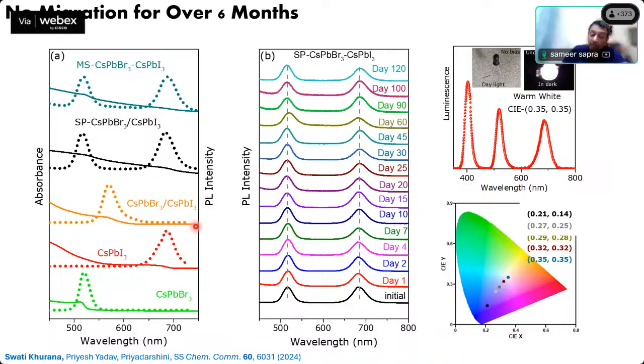Okay, and because of these vacancies, all these ions start to migrate. The bromides migrate towards iodide, the iodides migrate towards bromide, and you form a homogeneous solution of bromide iodide. You plug the vacancies when you add some amount of selenium or sulfur or tellurium. The moment you plug these vacancies, these iodide or bromide cannot move. And the other thing is that bromides and iodides happen to be ionic in nature, much like sodium chloride, salt. This is also a salt which is ionic in nature.